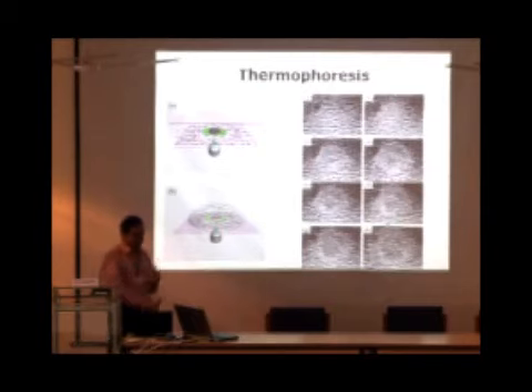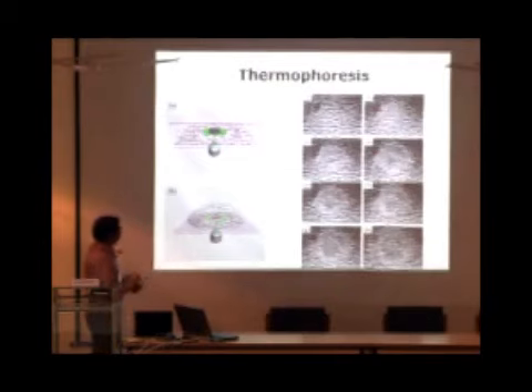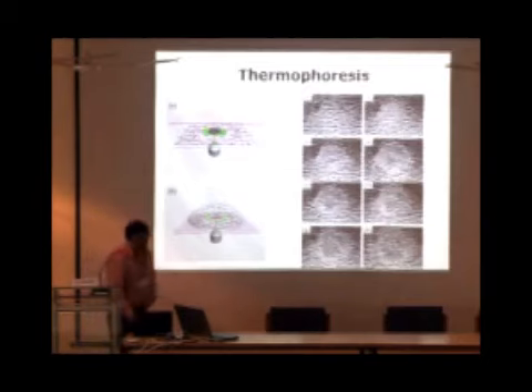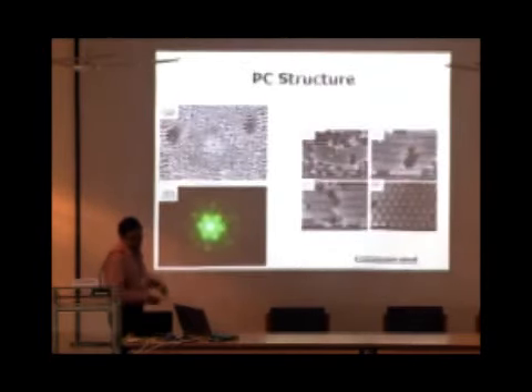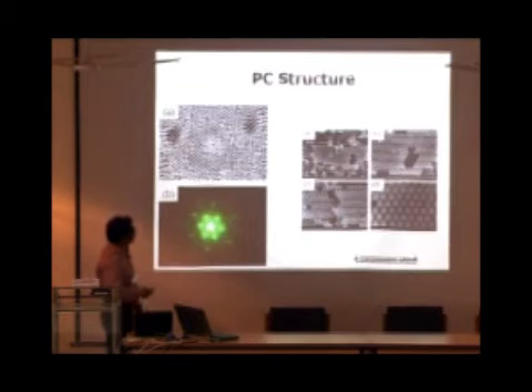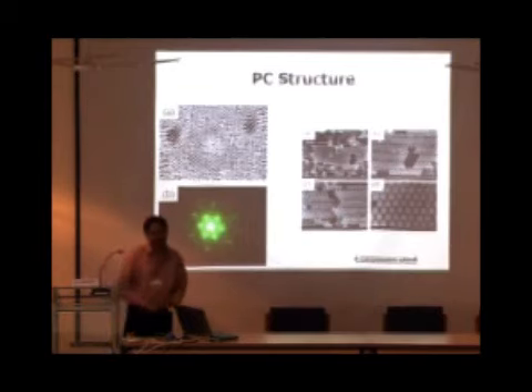What happens is if you use light, your trap light, laser light, and focus it, you're locally heating your medium. Because of this local heating, the magnetic particles move away from the heating region, which creates a gradient for the silica beads to move inside. You can use this to get close packed structures once again. We've seen 5 to 7 layers of this stack of silica beads, and you see a nice diffraction pattern when the periodic structures are formed.